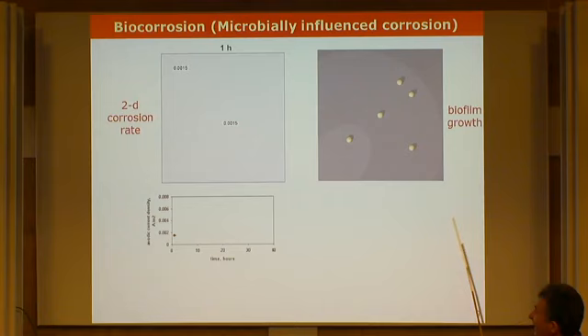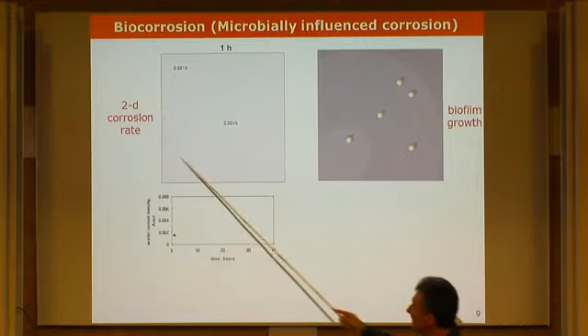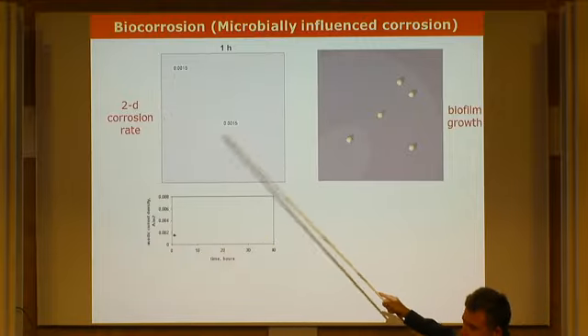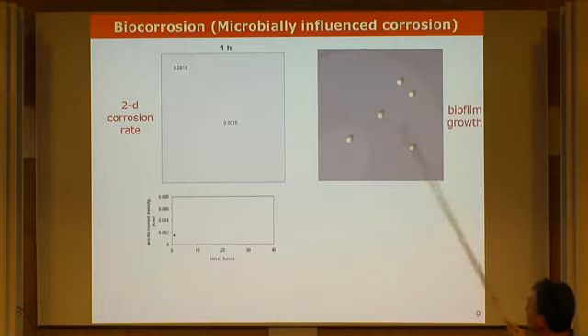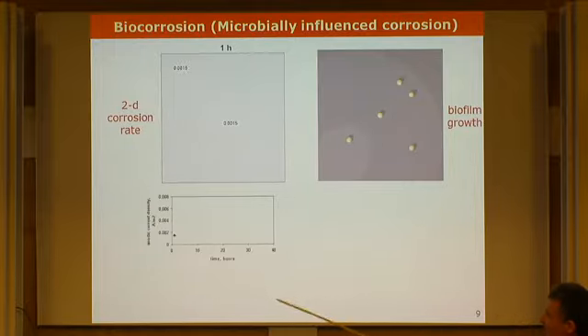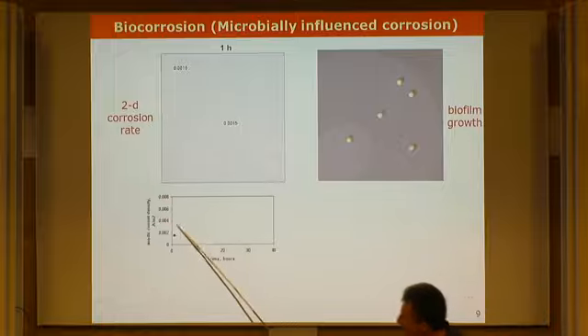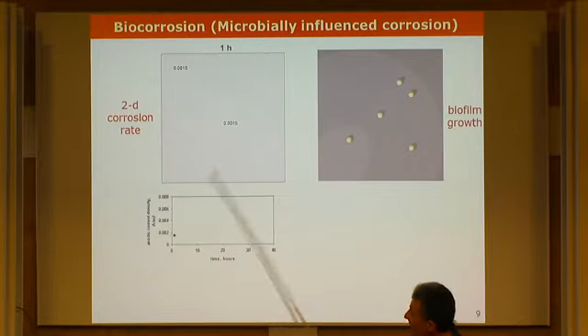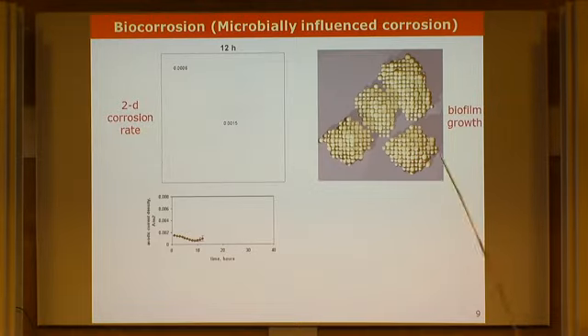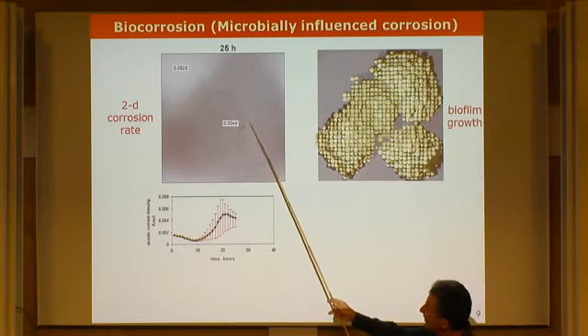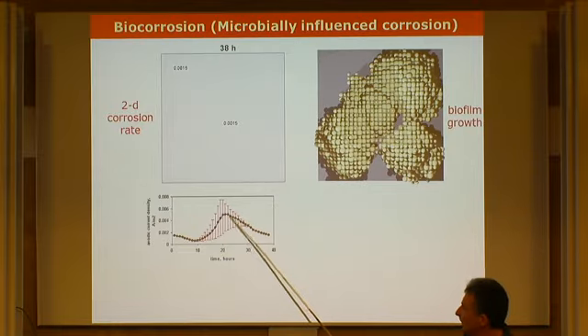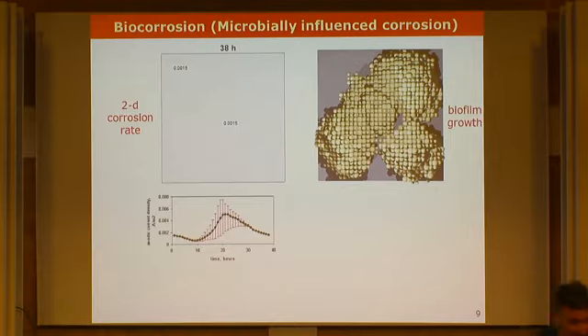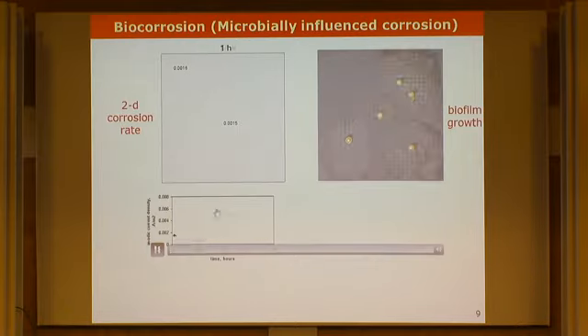And here I have a little animation. This is typical for my presentations. A little animation with what happens in time. This is the corrosion rate you will see here. White means less and black means more corrosion. Here you will see biofilm growth starting with 5 cells. They will make 5 colonies here. And this is the current density, practically is the corrosion rate integrated over the surface. So if you run this a bit, you will see how the cells grow, how you have a maximum in corrosion, and then how the corrosion current actually decreases after a while.